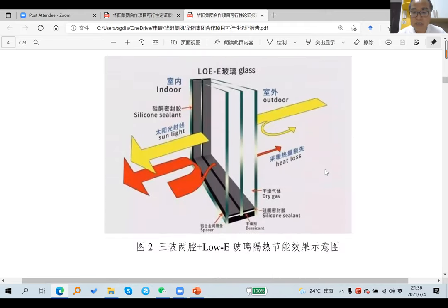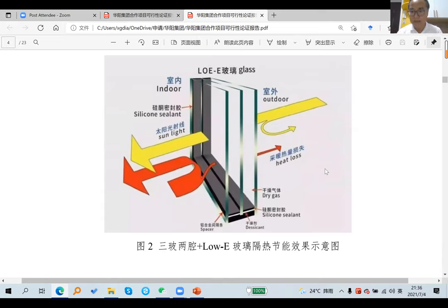In order to make windows more efficient, more energy saving, more thermally insulating, a triple glass with two chambers has been developed, also with low emissivity coatings on the glasses. So it can be very energy saving. But the problem with this kind of window is that it is very heavy, because there are three layers, each layer of glass with its thickness, and the spaces. Therefore, people developed other types.